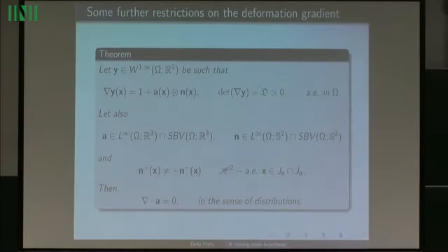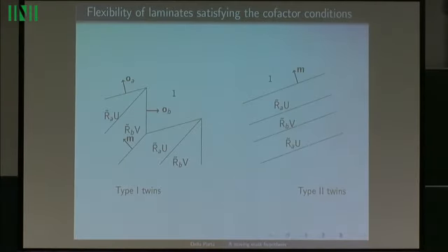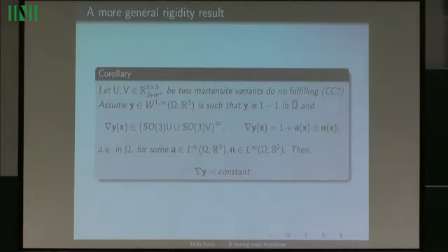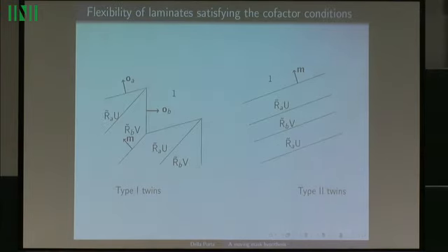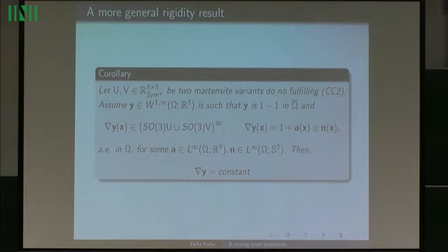If we consider simply the two martensitic variants case, and you satisfy this constraint and you have a laminate constructed with just two martensitic variants, you can construct the interfaces provided that your image lies in a one-dimensional curve of finite length.